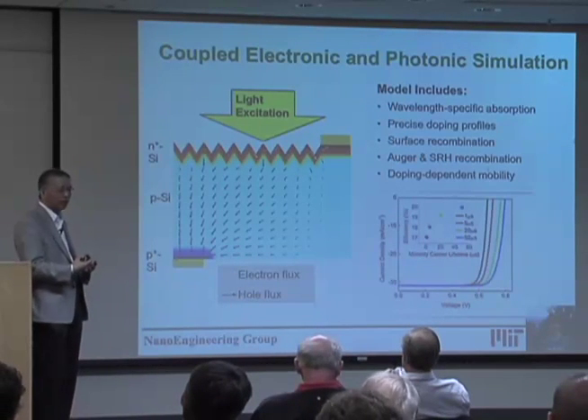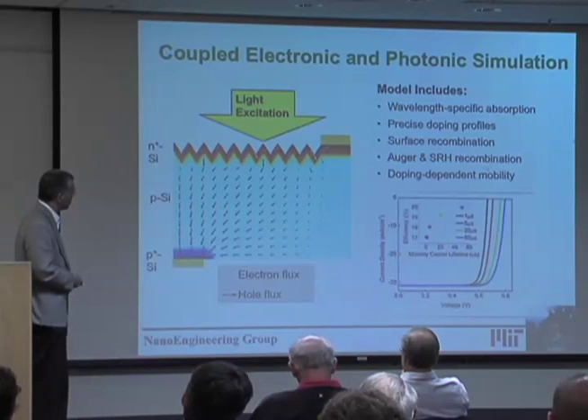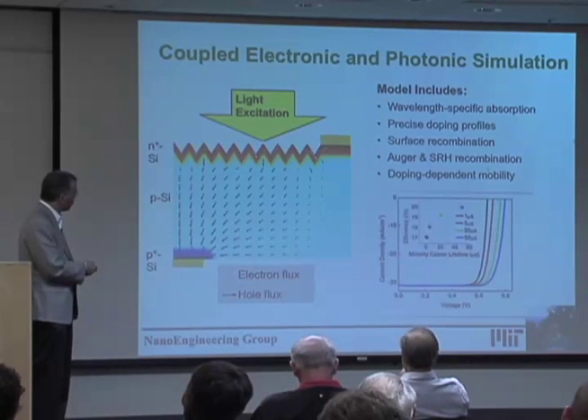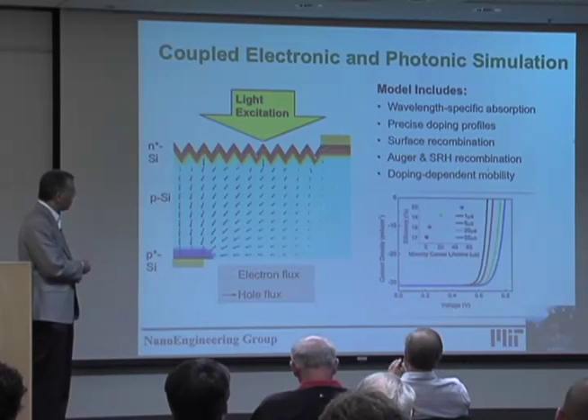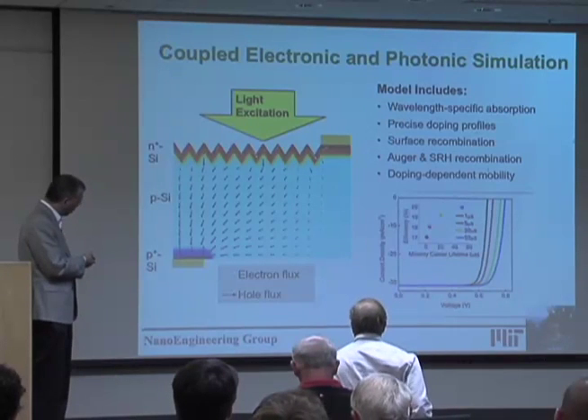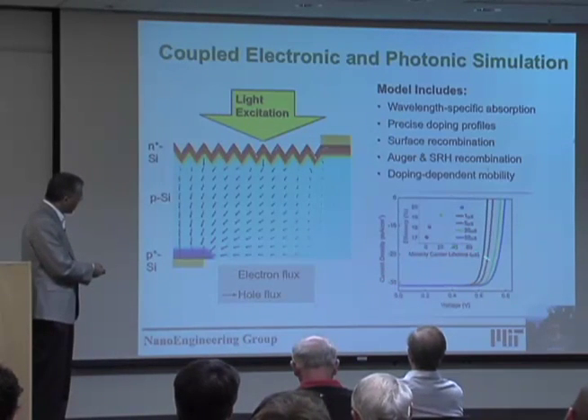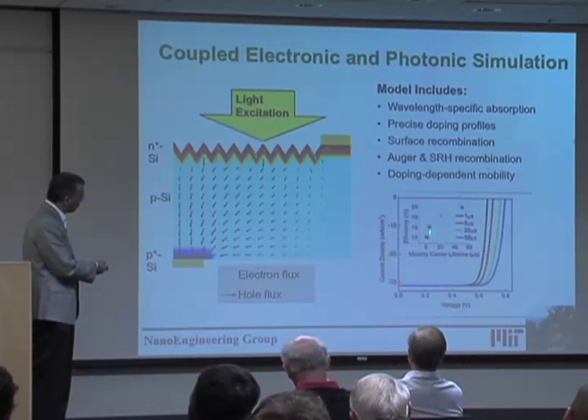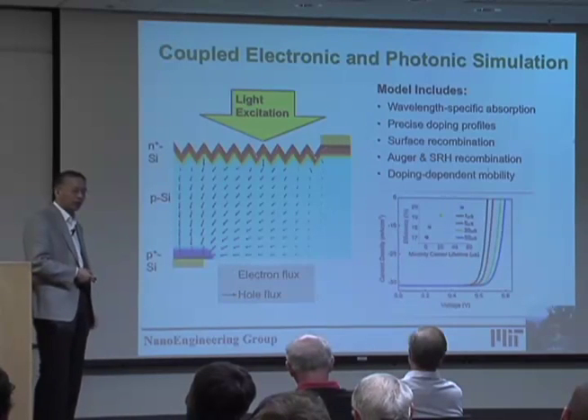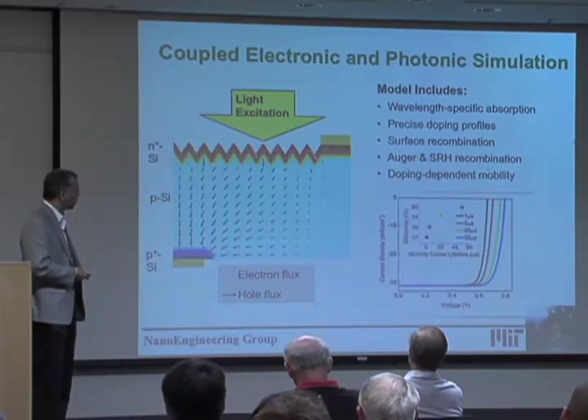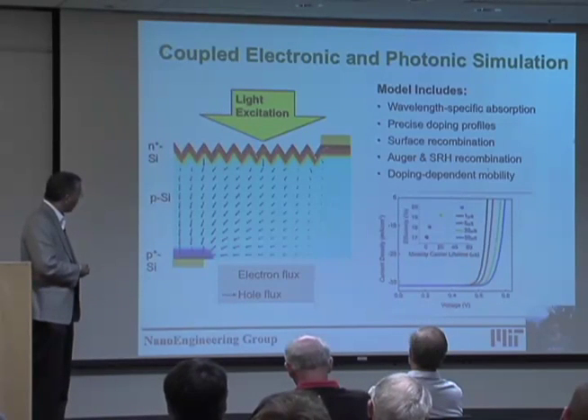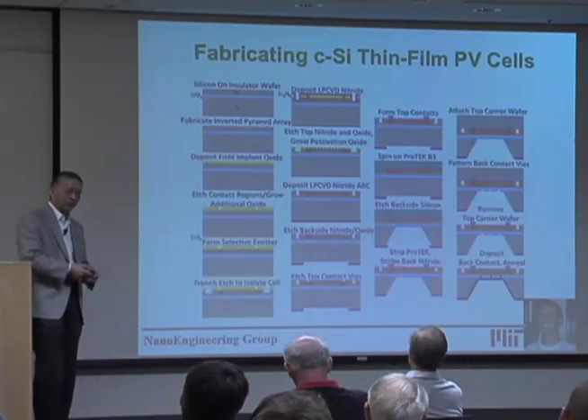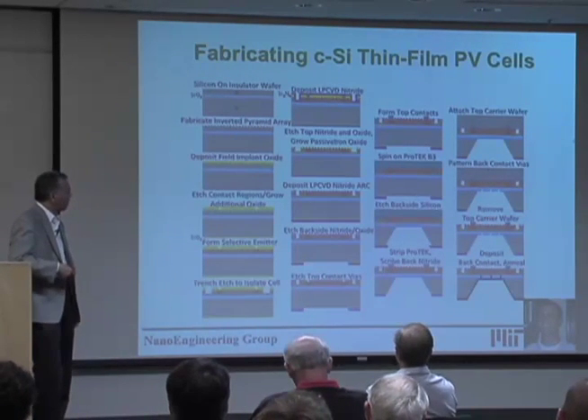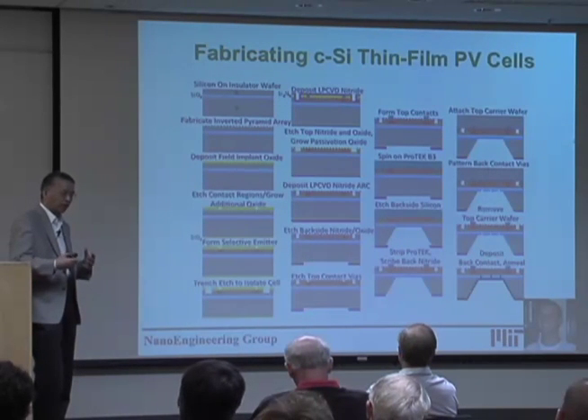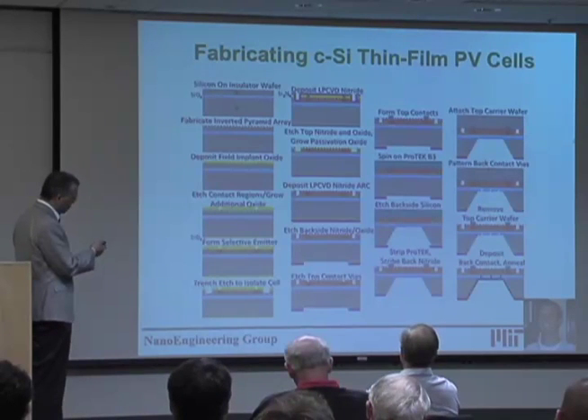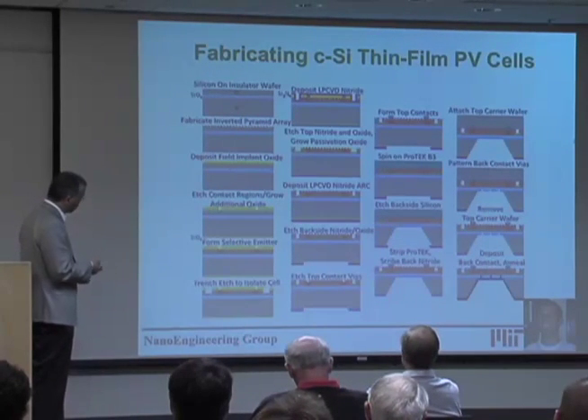Stitching this together actually took some time. We considered all the effects: surface recombination, bulk recombination, and how to do the different doping and electrode profile. Our goal with those simulations was to see if we might achieve 15 to 20% with a less than 10 micron silicon cell. With that, we had a very brave graduate student go to the clean room using an SOI wafer. It's a lot of fabrication steps, and I'm not going to go into detail.